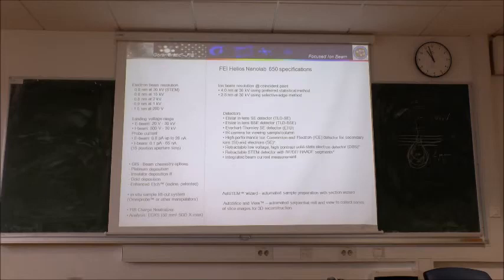Electron beam, this is the scanning electron microscope, it's really good resolution. Also at 1 kilovolt, it's below 1 nanometer, and this is due to the monochromator. This column has a monochromator at the top, just below the electron source, which even improves the resolution at lower energies. Ranges from 20 volts to 30 kilovolts. We are still talking about the electron beam. The landing voltages for the electron beam are 20 volts to 30 kilovolts, and for the ion beam half a kiloelectron volt to 30 kiloelectron volts.